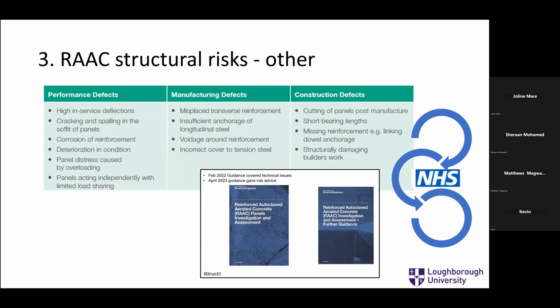Some of these other defects can lead to that. Voidage around the reinforcement, deflections. If you've got your plank sat on your bearing and it's not very big, that's a problem. But then if you're deflecting, suddenly you've just developed a nice stress concentration at the point just where the crack wants to develop and propagate. So deflection isn't going to fail it, but deflection can exacerbate the problem. And there's other defects that can exacerbate the problem.